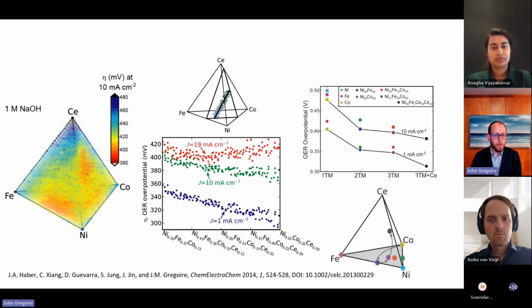The system that I'll focus on for the next few slides is using that 4-element combination as I described before for the printing. This is iron, nickel, cobalt, and cerium. What I'm plotting here is a heat map of the overpotential, but here I'm taking a particular composition line that starts from a transition metal composition and cuts through the space to a 50% cerium composition.